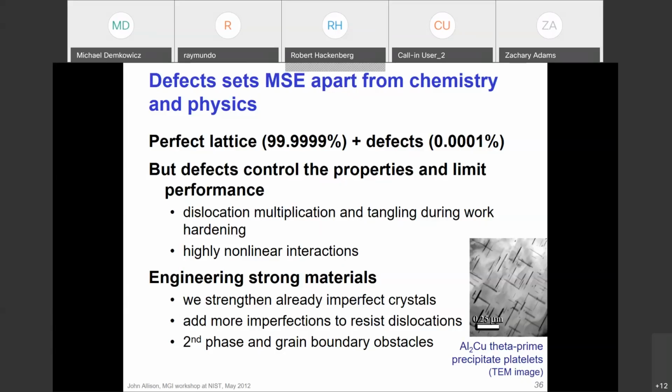Having these, the really important thing is to have these homogeneously dispersed, because the dislocations will find a weak point. If there's any weak point where there's a really big gap between the nearest cluster of precipitates, it'll just blow through there, and that's where dislocations will pile up, you get an incipient crack, and then things fail. So you really want to homogeneously distribute it. And that's actually not necessarily easy to get. But we learned a trick, and it came about through studies of age hardening.